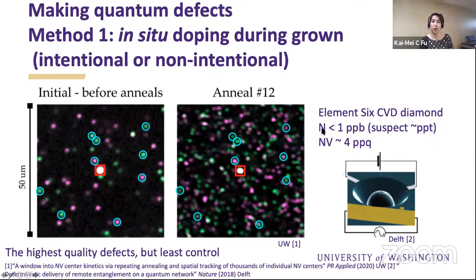There are so many more defects in the crystal than you can possibly see. What is nice is that these defects will be as nice or nicer, because you've been annealing for a long time, than the defects here. So you don't need this concentration of defects, because these have all these other defects that you can't see or utilize yet in there. It's just that we've turned more of them into NV centers in this case.